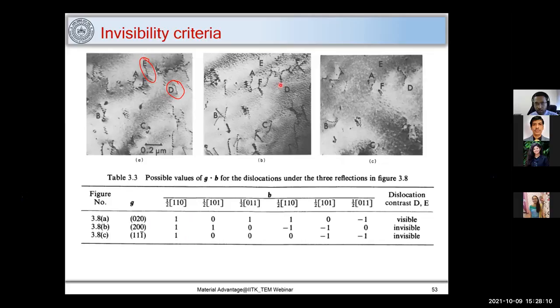Here in this case, that is corresponding to G equal to 200, and this case is corresponding to G equal to 1 bar 1 1. Here you can see that the E and D dislocations have vanished, and that can happen only when they become invisible. So this is the only condition. Let me mark here. This is the only Burgers vector which satisfies this condition. So the Burgers vector which we can identify from this rotation or tilting of the sample is half 0 1 1 in these two cases. A dislocation will be invisible if G dot B is equal to 0, and there will be weak contrast if G dot B is less than 0.